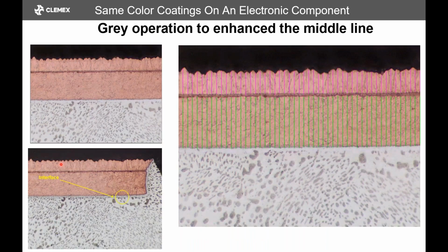Right, so we have another coating here where we have a different challenge. We have a coating that has the same color, top and bottom, but we need to measure both. So we have a line here that is also a very similar color. So we can use an edge finder to detect the line and separate the coatings from each other, and then measure the line separately.